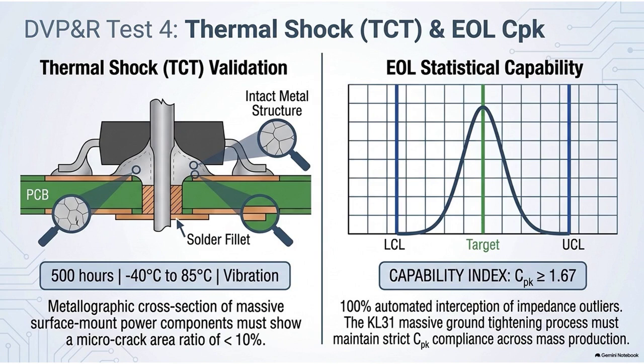And after 500 hours of this torture, it's not enough that the board simply powers on. The validation criteria goes down to the microscopic level with a metallurgical autopsy. That's right. They take the surviving boards, embed them entirely in blocks of clear epoxy resin, and use diamond saws to physically slice the PCB and the solder joints perfectly in half. They polish the cross-sections and place them under high-powered scanning electron microscopes. They're looking at the grain structure of the metal itself. They're measuring the propagation of fatigue cracks along the intermetallic compound layers.